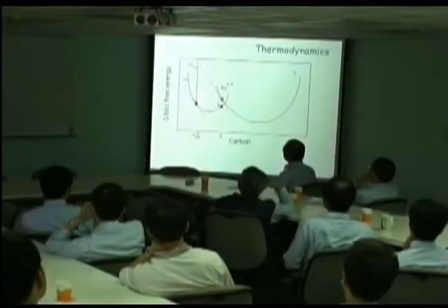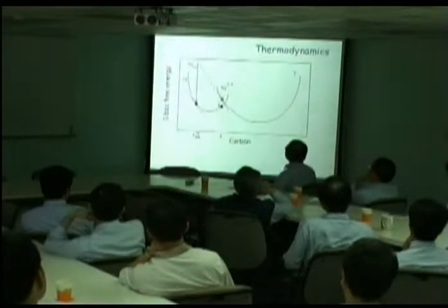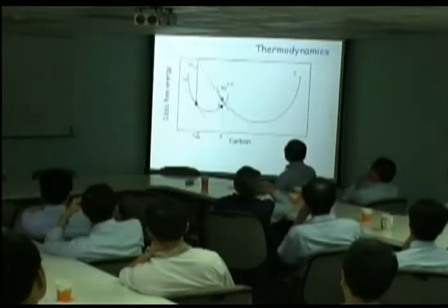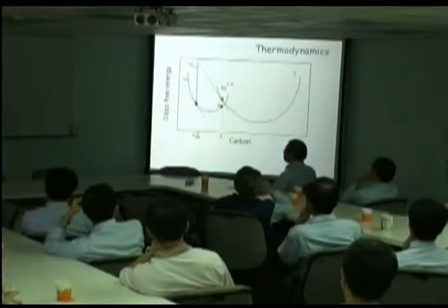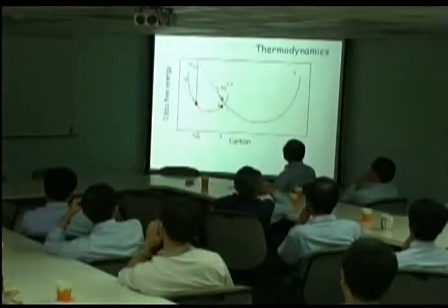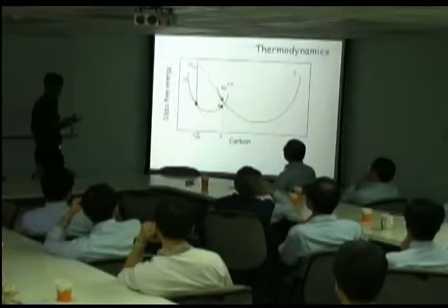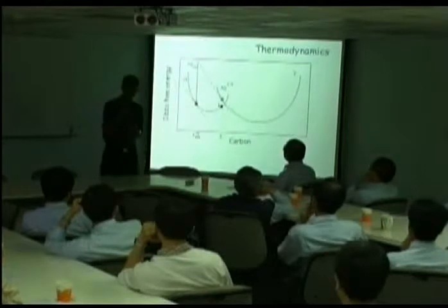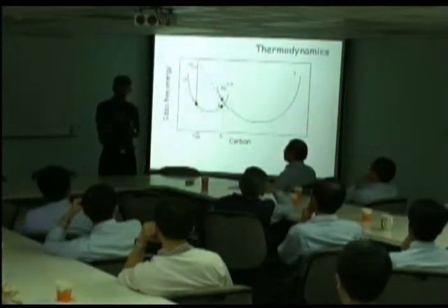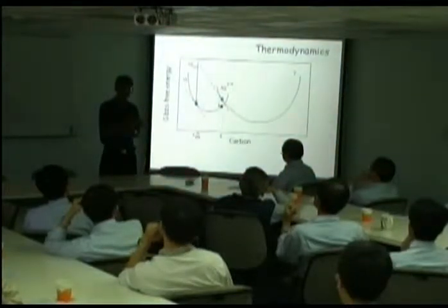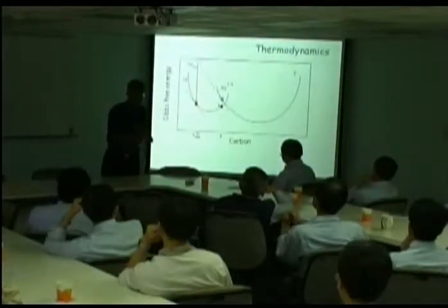Okay. On the other hand, if I nucleate a phase but allow carbon to diffuse, then I get a much larger free energy change here, which I will call delta Gm. So what I want to do is discover whether during nucleation the nucleus is also forming without any diffusion, or whether carbon has to diffuse during nucleation.